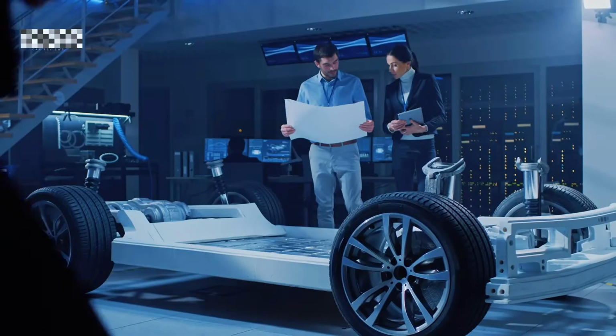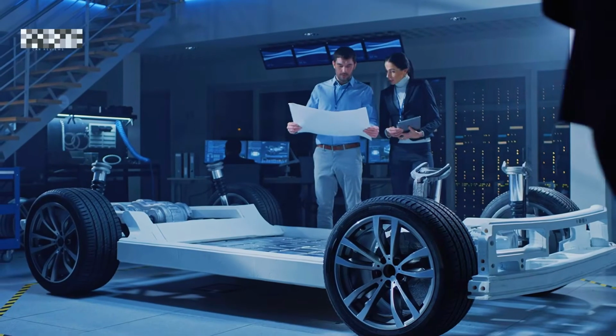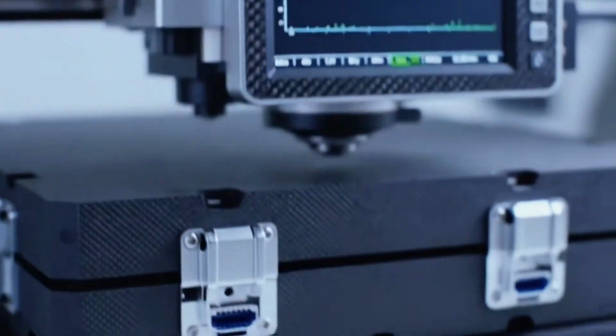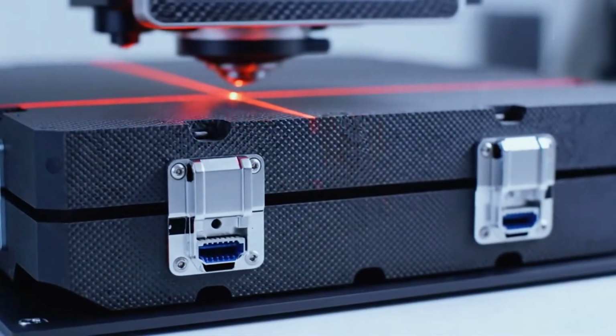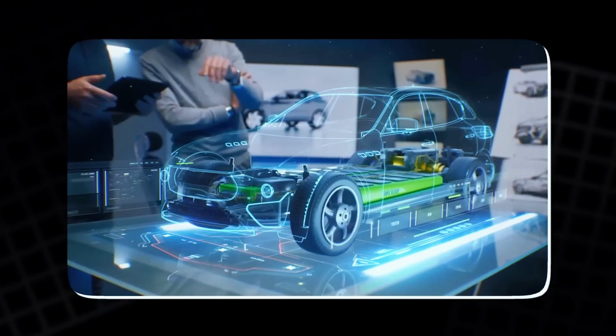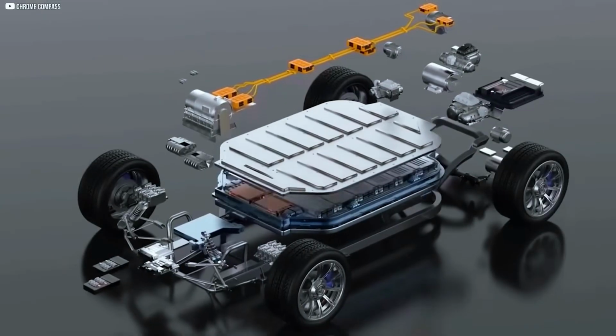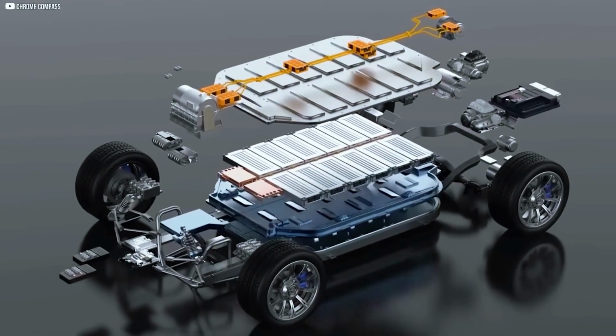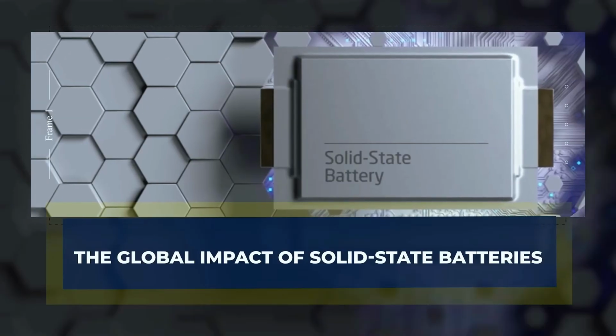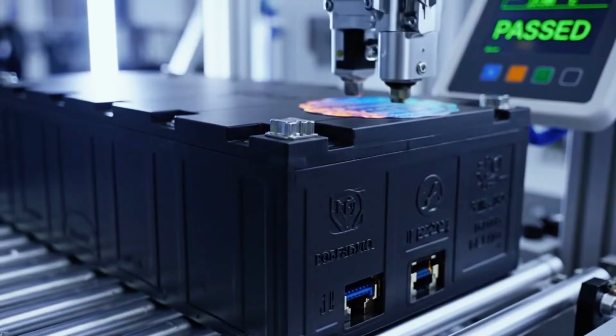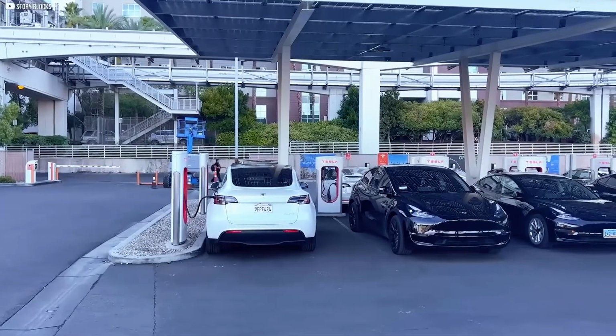Longevity. Without liquid electrolyte degradation and with mechanically suppressed dendrite formation, solid-state cells have demonstrated cycle life exceeding 1,000 full charge cycles, with less than 10% capacity loss. Some laboratory results indicate 2,000 to 3,000 cycles is achievable, which would represent 2 to 3 times the usable lifespan of a current EV battery pack.